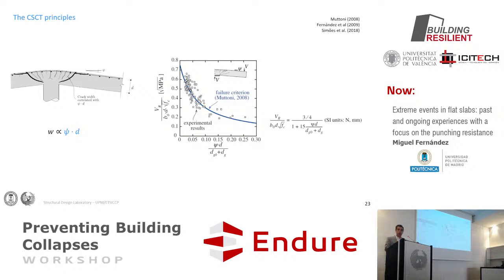Because as you were showing in your long-term test, you were stating that the strength, the resistance, was rather constant, while the rotations were increasing, the deflections were increasing. And this may seem contradictory because you will say, okay, but if psi increases, then the resistance shall decrease. No, not at all, because the parameter is not the rotation. Rotation is what is giving us an idea of what's happening. The parameter is the opening of the cracks.